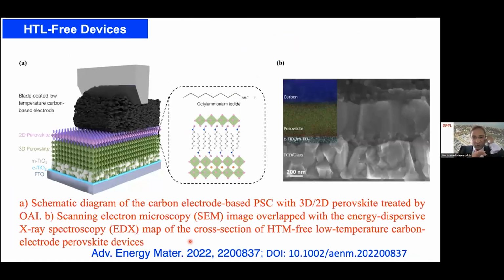Now, can we get rid of this hole transporting material completely? So here is one configuration. This appeared just last month. This is joint work between the Fraunhofer Institute and our group, so we are collaborating on this topic. Here is the configuration. It's the same as before: we have a conducting glass, a compact layer of TiO2, and a mesoporous TiO2 layer. We deposited perovskite followed by the two-dimensional perovskite. But instead of depositing a hole transporting material, here carbon is deposited, which acts as a hole transporting material and at the same time replaces gold as a contact. However, you have to pay the price because the efficiencies are not the same as the previous configurations.